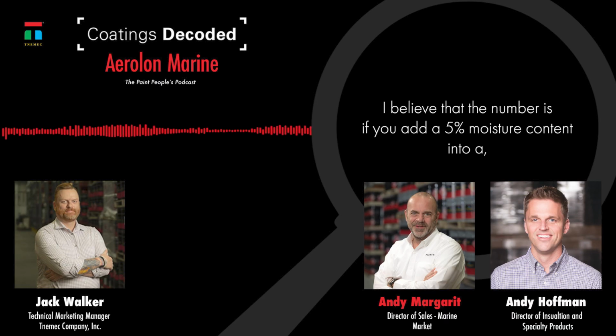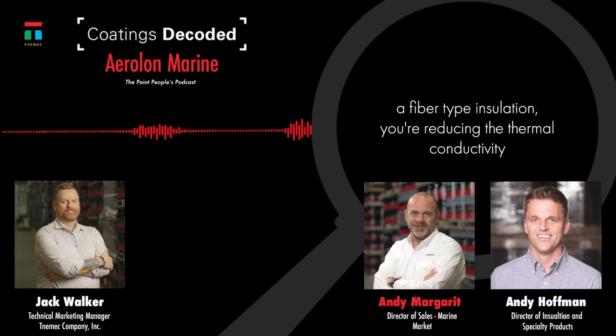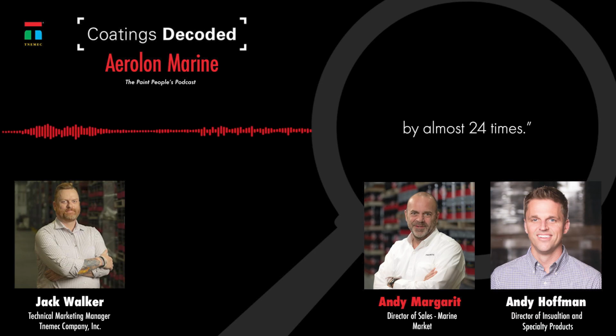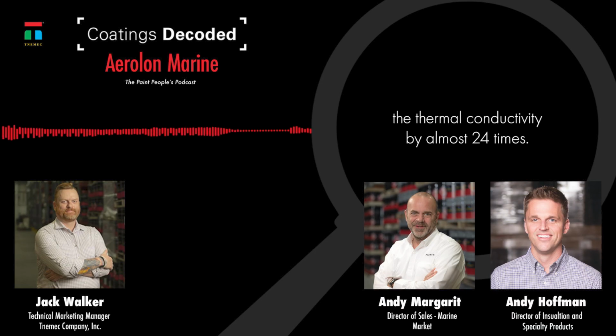I believe that the number is, if you add 5% moisture content into a fiber type insulation, you're increasing the thermal conductivity by almost 24 times. Moisture increases the thermal conductivity by almost 24 times.